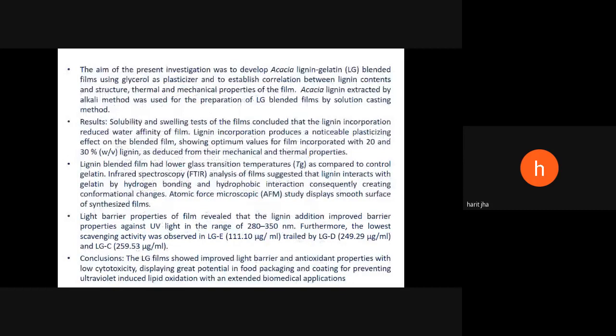This is another work which we already discussed: the synthesis and characterization of acacia lignin gelatin film for its possible application in food packaging. Here we have used the acacia lignin and gelatin blended film using glycerol as plasticizer to establish the correlation between lignin content and structural, thermal, and mechanical property of the film. Acacia lignin extracted by alkali method was used for the preparation of lignin gelatin blended film by solution casting method.